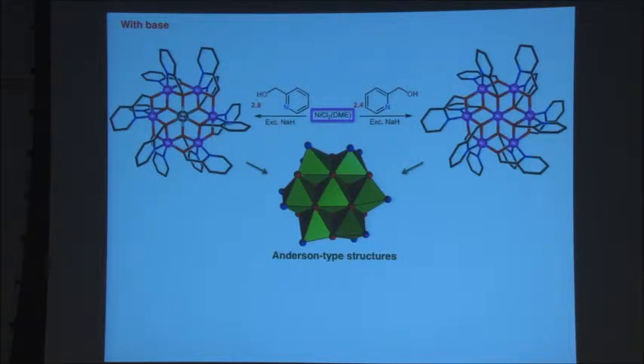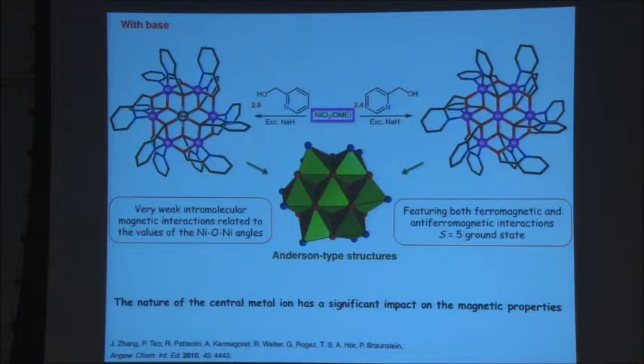And this is a structure which is very common in a completely different area of chemistry, which is that of polyoxometalates, high oxidation state molecular oxides, the so-called POMs. They have the structure which is named after Anderson type structure. So that's always fascinating for me to see that from different areas of chemistry, you suddenly converge to structural motifs that have been seen in other areas of chemistry. There are some links there.